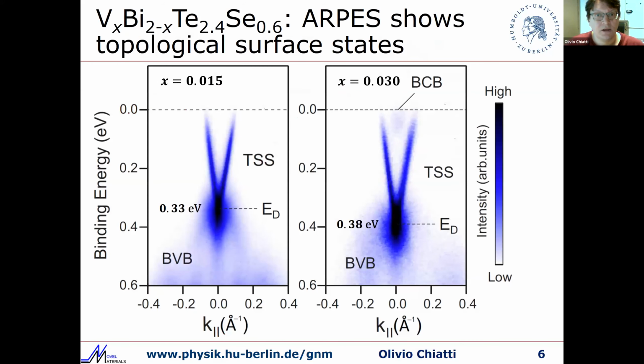So if you look now at the vanadium bismuth telluride selenide samples, we have some ARPES measurements for 2 samples of different vanadium concentration. One is 1.5% and the other one is 3.0%. The sample with lower concentration shows very nice topological surface states with a Dirac point at 0.33 electron volt binding energy.